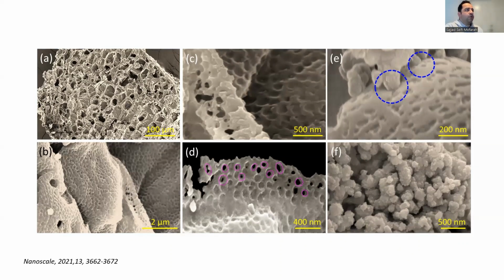And during heat treatment, we actually made perforated graphite and carbon-based materials. The very important thing about the presence of this perforated structure is that iron oxide can get trapped and locked into these perforations, and it can improve the charge transfer process and also the electrical conductivity, because as we know, iron oxide doesn't have good electrical conductivity, which is one of the requirements for energy storage performance.